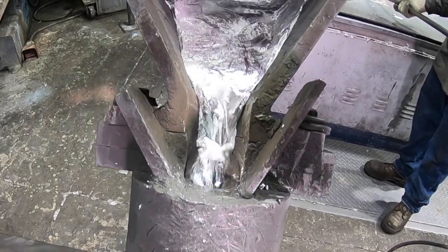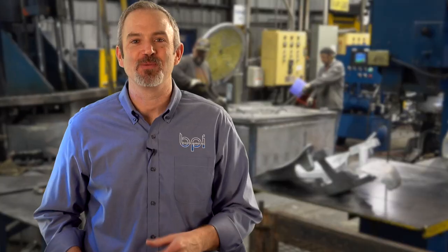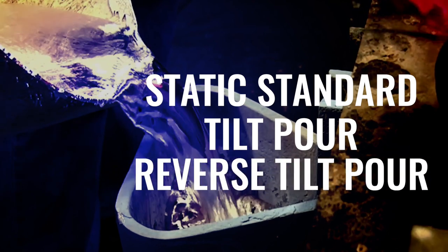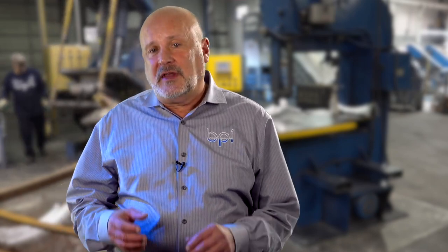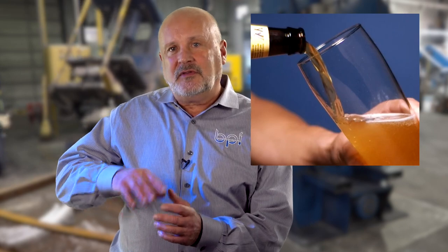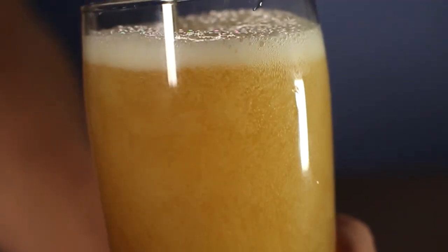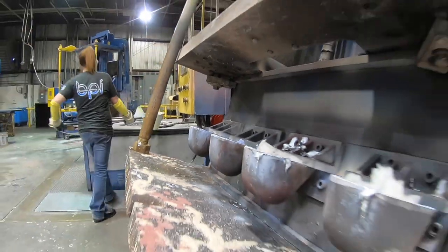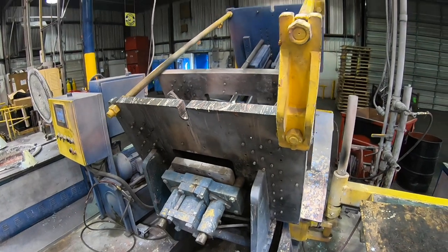Permanent mold casting uses a gravity-fed process. What makes us unique here at Batesville Aluminum Castings is we use three types of pouring methods: we have a static standard — that's an old tradition — we have tilt pour, and we have reverse tilt pour. We're one of the few foundries in the United States that do all three in-house. Tilt pour is pretty easy to understand — it's like pouring the beer down the side of the glass. You get less turbulence, you get less head. The more turbulence you get, the more air pockets are created. You don't want that in your casting because that is gas, that's porosity, and you don't get as dense or as hard of a part. It can cause problems in powder coating or finishing, makes machining more difficult, and will make the part weaker.